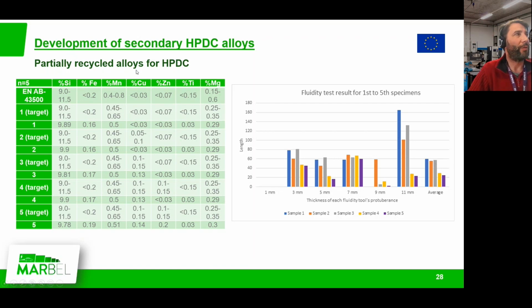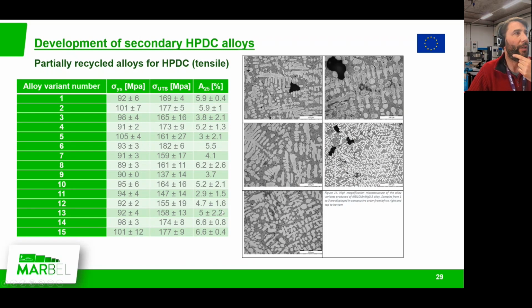And then we have also worked on the development of alternative additions of other elements in order to improve the robustness of the alloy against the variability of impurities present. Okay, here also we have done the fluidity analysis. We have observed that with additions of some elements such as zinc, fluidity is highly decreased, and well, this shows the impact of these impurities or the different elements one by one. And even if we can again observe an important effect in fluidity, in terms of mechanical properties they are not affected.